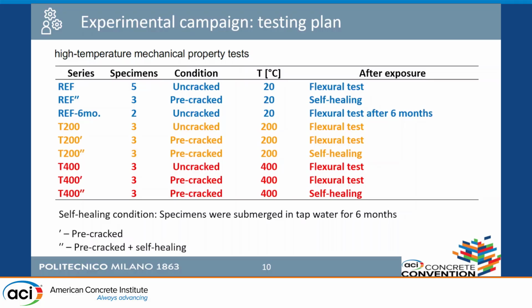This is important because also Dr. Wiley discussed in his presentation the chemical processes that take place in concrete from 100 to 1,200 degrees C. But the large share of the irrecoverable chemical processes start at 450 because we have the decomposition of the portlandite. So starting from 450, the concrete starts to be damaged, seriously damaged, and during the cooling we don't have important recovery. So typically we have to remove the concrete that overcomes that temperature.